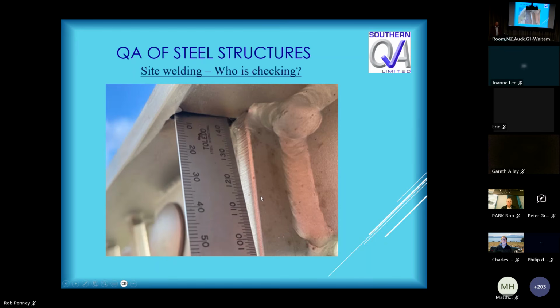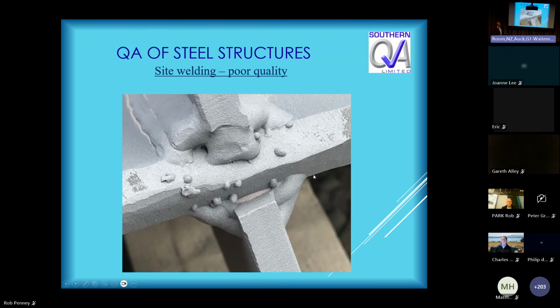So who's checking? This is the sort of stuff we sometimes come across. There's a bit of a defect there when the end of your steel rule disappears into the groove. Coating's not going to work very well on there, is it, Sean? That's one of the issues. That one is just some probably relatively small gussets, and the ends of the welds aren't cleaned out properly. And you've got these horrible looking lack of fusions, and all these horrible chunks of spatter. The problem with that is just as big for the coating people as it is for the welding people. Your coatings are not going to last 5 minutes on there.